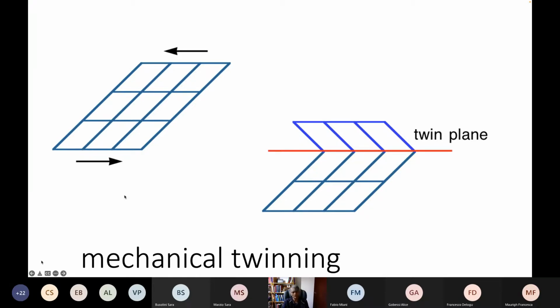And what do we mean by a twin? Well, supposing that I have a lattice like this, and I shear it homogeneously, then this part now reflects about the twin plane into the original structure. So this is a particular kind of twin that is quite common in the sort of steels that I'm going to talk about, where you can generate the twin lattice by a reflection of the parent lattice across the twinning plane. And of course, there's a physical deformation, which is a pure shear on the twin plane. So that is mechanical twinning.